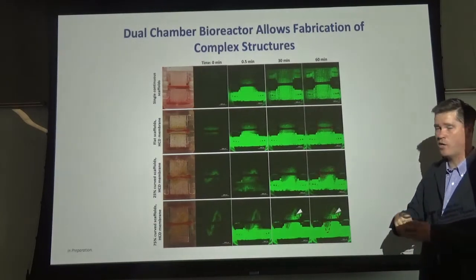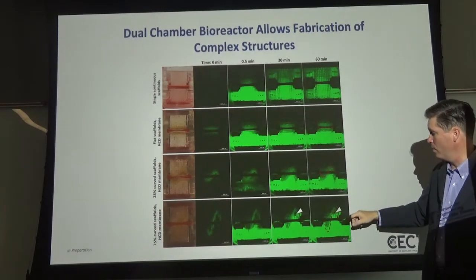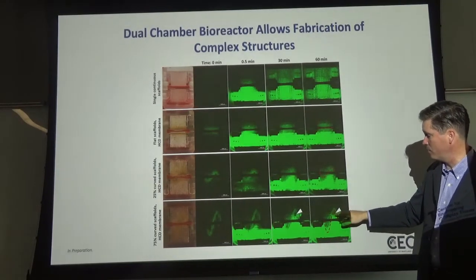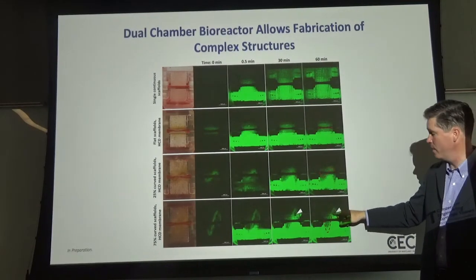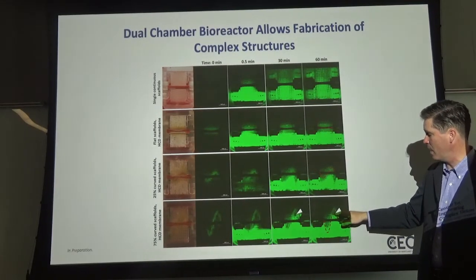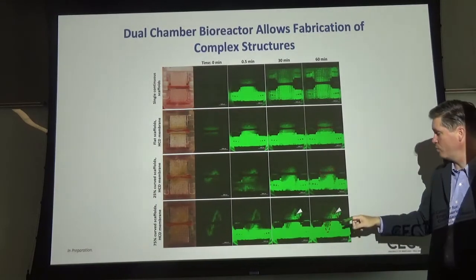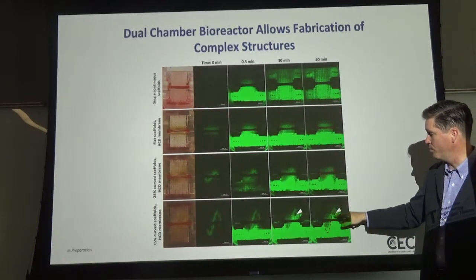When you extend that curvature, when you make it even more pronounced, you actually start to see some dead zones in the bottom scaffold. It's just the curvature is too much for simple diffusion, a little bit of convection to fill this bottom chamber.